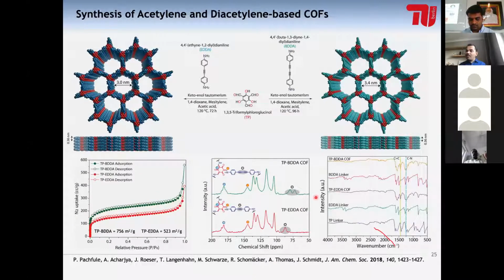Now, how do we know whether these moieties, acetylene, diacetylene, are there, and is there any imine linkage inside? We can do the 13C NMR analysis in a solid state. And here, what we found is that using 13C, we can definitely see that there is a presence of diacetylene moieties. The peaks representing them are present. There are acetylene moieties exactly at this particular location where we expect and simulate, and different linkages. For example, the imine bond is still intact, and every moiety which we expected is still there.